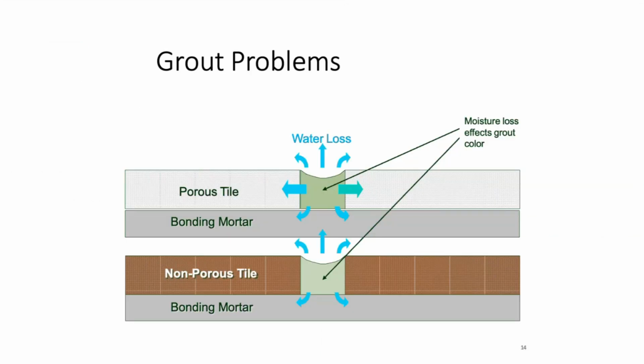So this is a little easier way to explain it. When you look at the top, you'll see it's a porous tile. So those were the ceramic tiles from the 50s through the 90s. You'll notice that when it's set into a bonding mortar, or what we would call a thin set bed, the moisture from the grout could hydrate downwards, upwards, and to the side. So it had a lot of chance for that moisture to hydrate evenly, so that the grout stood a better chance of not only hardening the way it was supposed to, but also retaining the color, which was very important to the end user and to us.